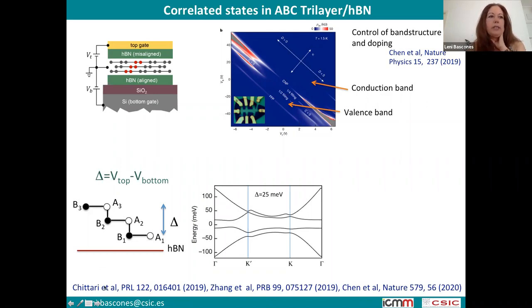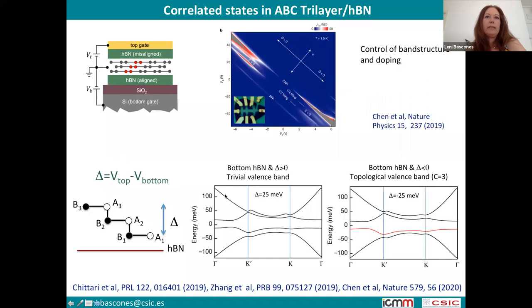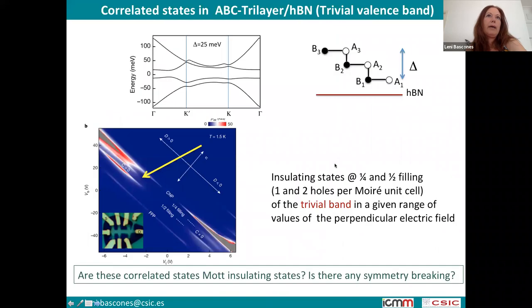This is because in this system in particular, we don't expect to have symmetry with respect to the sign, and that's associated with the fact that the boron nitride is aligned with only one of the layers. Depending on the sign of this field, we will have either a trivial band or a topological band. So I will talk about the case in which we have a trivial band.